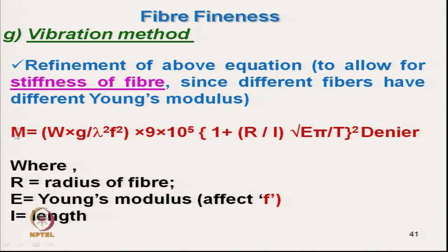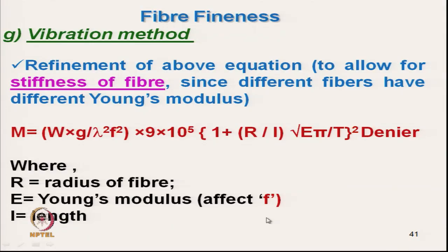This method is normally used for man-made fibers like polyester, which may have the same length and everything else, but different Young's modulus, and this difference in Young's modulus will lead to a different frequency.